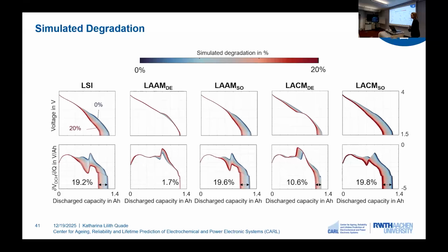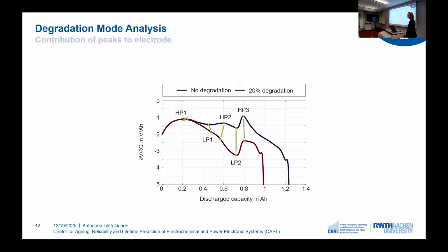So let's continue with the analysis of the peak evolution per degradation mode category. Here we can see again the category loss of sodium inventory, and we can now only focus on the case of no degradation and the 20% degradation. We can identify 5 characteristic peaks: HP1, high point 1 to HP3, and also LP1 to LP2.